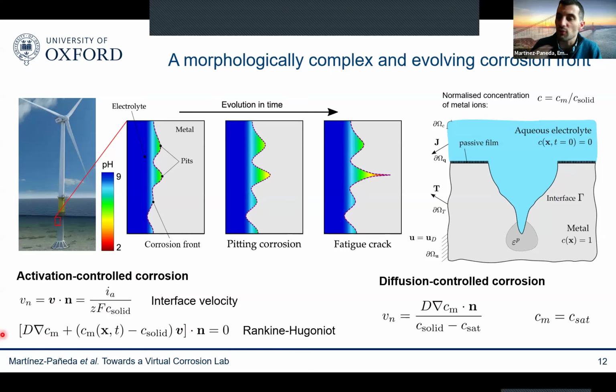But then if I have diffusion control corrosion, so if I saturate the number of ions in my interface, and we need to wait for those ions to move away within the electrolyte, then the velocity of the pit is given by substituting the saturated concentration, the Rankine-Hugoniot condition, and the concentration of metal ions in the interface is given by the Dirichlet boundary condition.